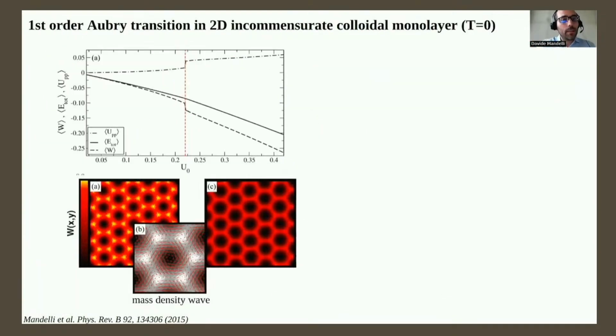And in fact, if we continue increasing the substrate potential, we do observe a first order structural transition, which is signaled in this plot by the presence of a jump of the interparticle Coulomb potential energy at the critical region, which jumps up, and the corresponding jump downward of the substrate potential energy. The total energy, which is shown here by the continuous line, must be continuous, and shows a kink here, which is a discontinuity in the first derivative. This is a signal of a first order phase transition. And again, what is happening at the critical point is that these shear modes lead to a local rotation of the colloidal monolayer back into registry with the substrate potential.